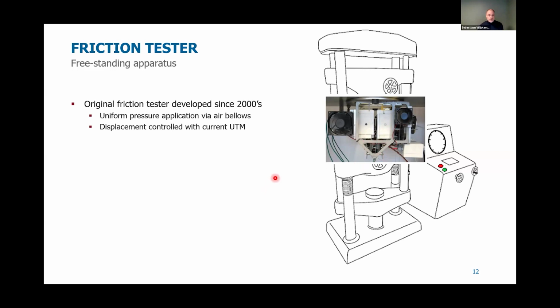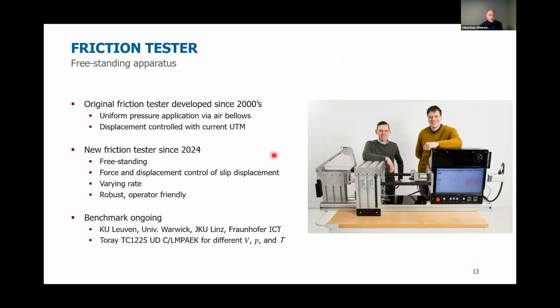growing importance of good, robust measurements, we decided to develop a new friction tester. We have considered upgrading the previous one, so we would be able to use it in a universal tensile testing machine. In the end, we decided to go for a freestanding unit. So here's a clamping and heating device. Here's a cylinder that can pull the ply from the two plies here.